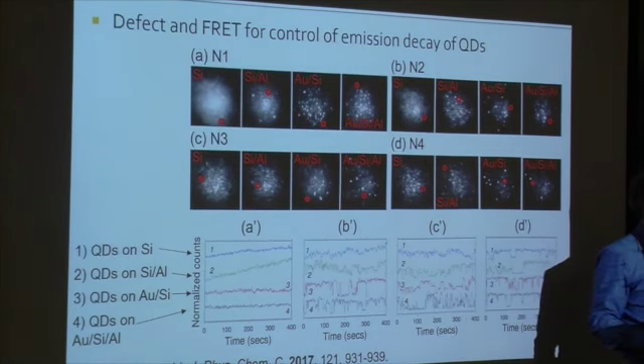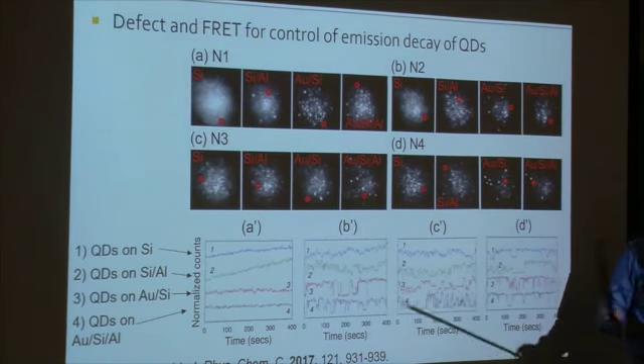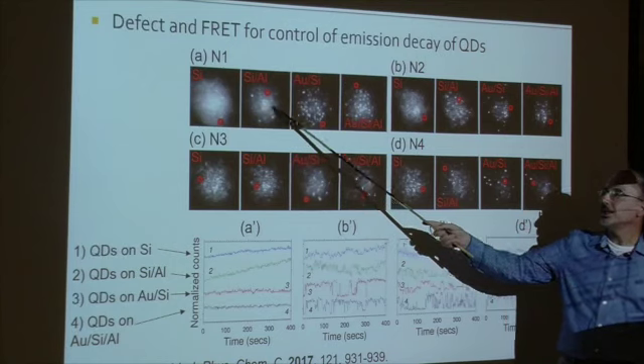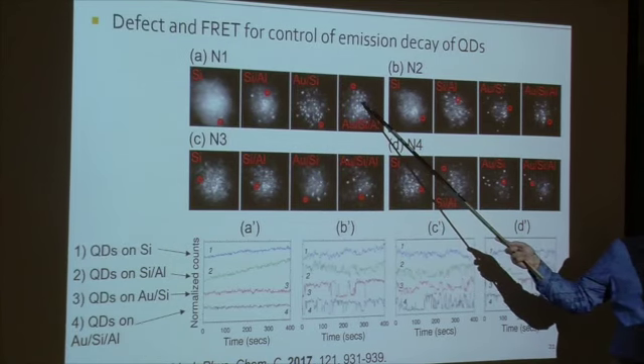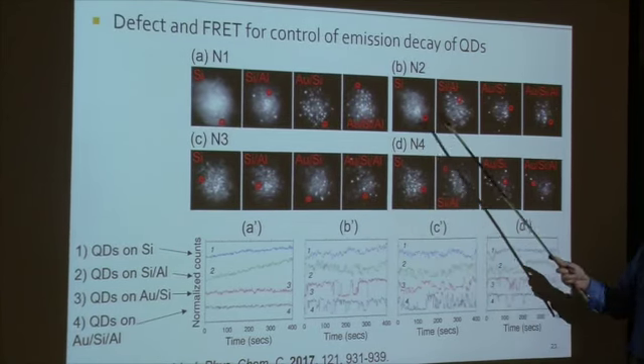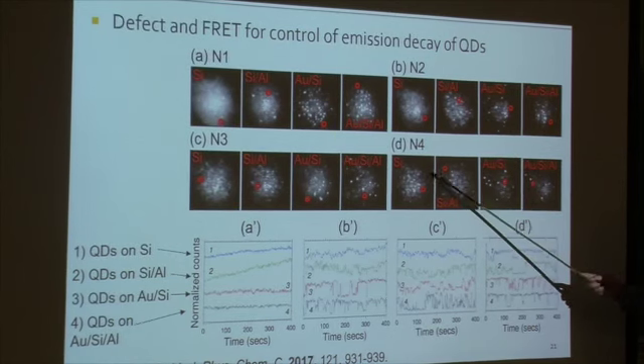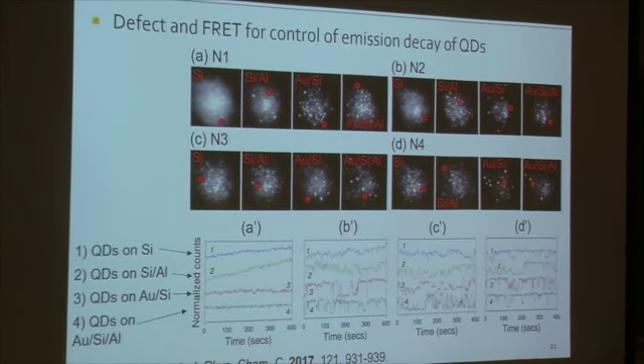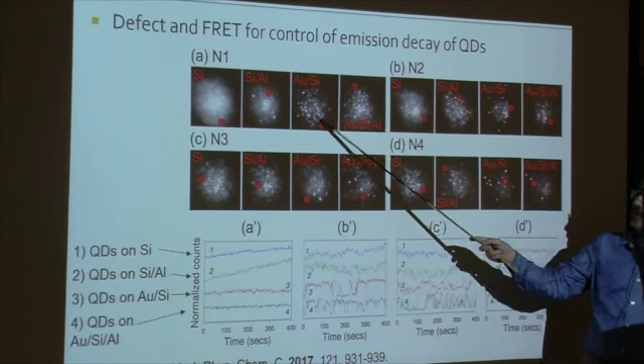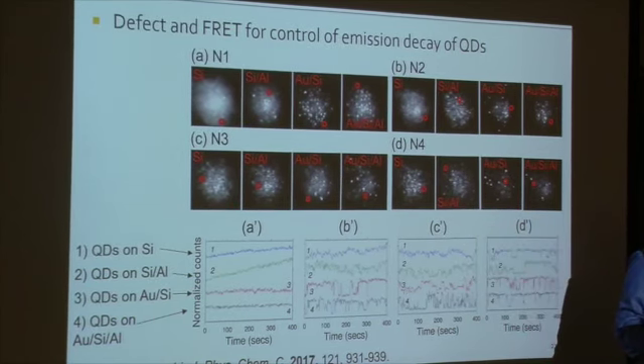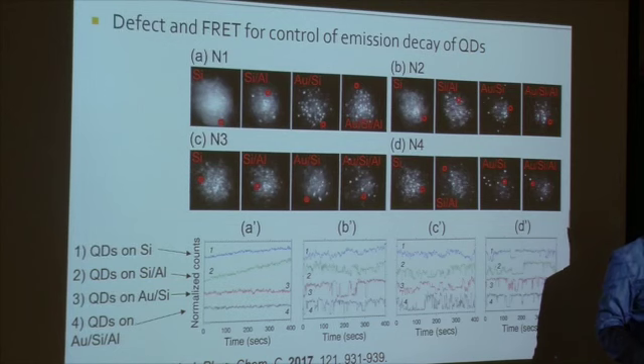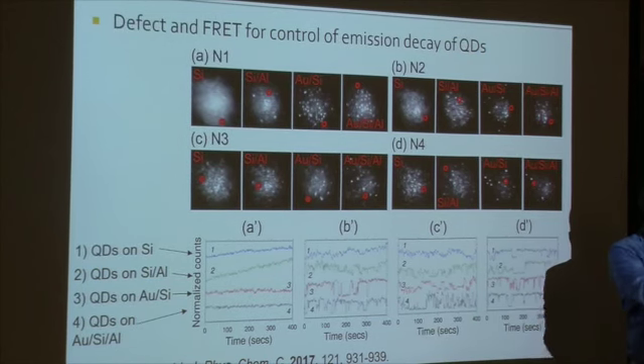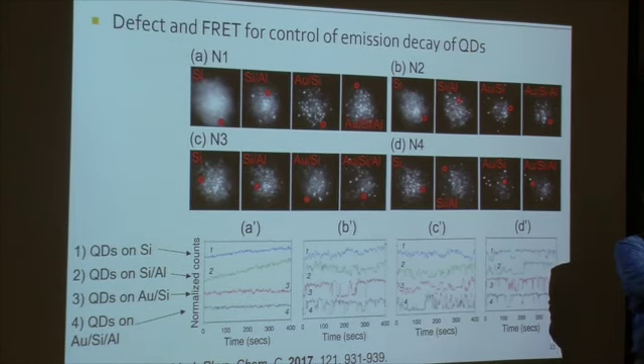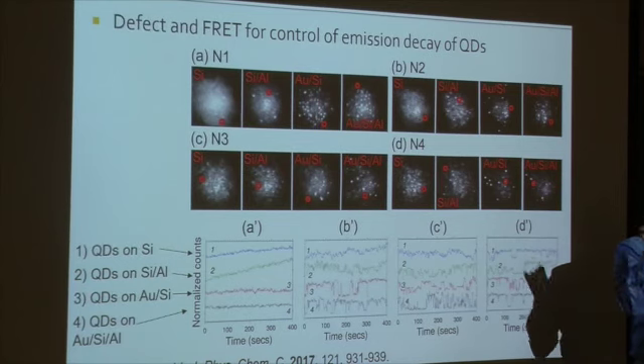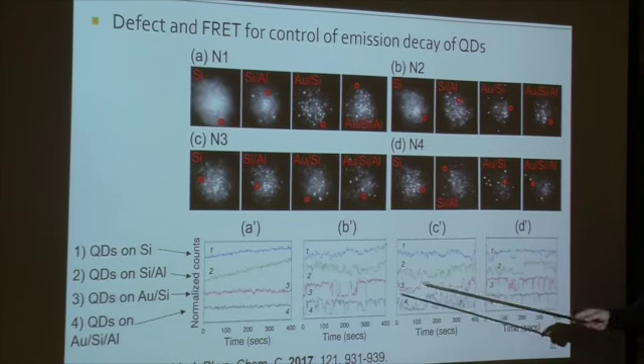And this is taking an image of the sample. So this is N1, a high concentration of the quantum dots, a little bit lower, and N4 is the single quantum dot regime. And those circles that you see are sampling points. We put the light detector at that point, and we collect the emission from that point over a period of time. And this is what we obtain.